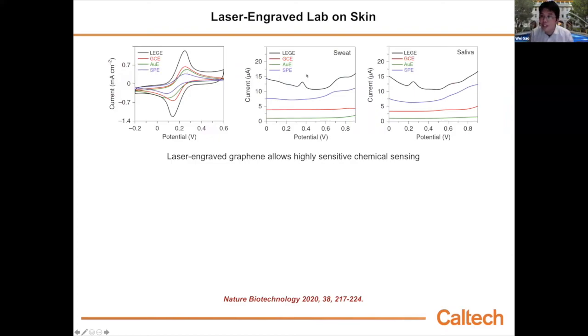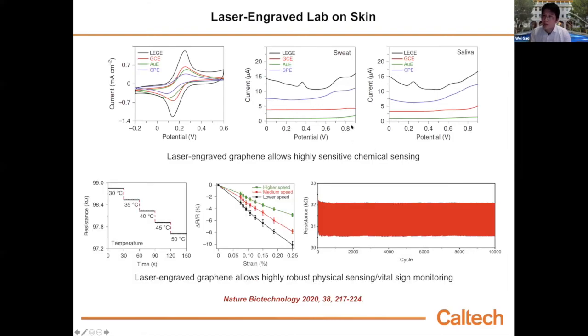If we do a DPV scan in a sweat sample, we see two significant peaks from our graphene electrode. The one on the left belongs to uric acid, and the one on the right belongs to the amino acid tyrosine. But for other traditional or classic electrodes, we don't see significant peaks in sweat or saliva samples. That means our sensor has very good performance for chemical sensing.